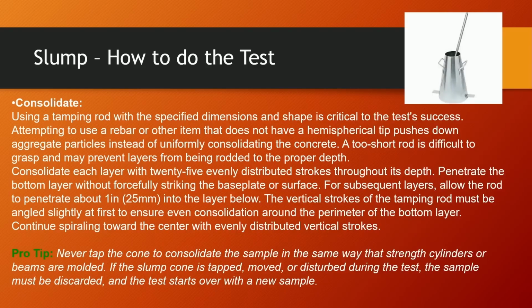Okay, consolidate. They're going to use that tamping rod with specified dimensions and shape. It's very critical to test success. Attempting to use a rebar or other items that do not have a hemispherical tip pushes down aggregate particles instead of uniformly consolidating the concrete. A too short rod is difficult to grasp and may prevent the layers from being rodded to the proper depth. You've got to consolidate.